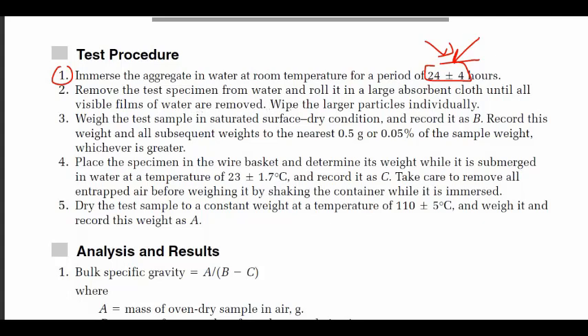Wipe the larger particles individually. As we said, we are drying up the sample, so we remove the test specimen from water and roll it in a large absorbent cloth, and for the larger particles try to wipe them individually. And step 3, we are going to weigh the test sample in saturated surface dry condition, as we said, and record it as B. So we're going to give this the variable B. Record this weight and all subsequent weights to the nearest 0.5 g or 0.05% of the sample weight, whichever is greater.